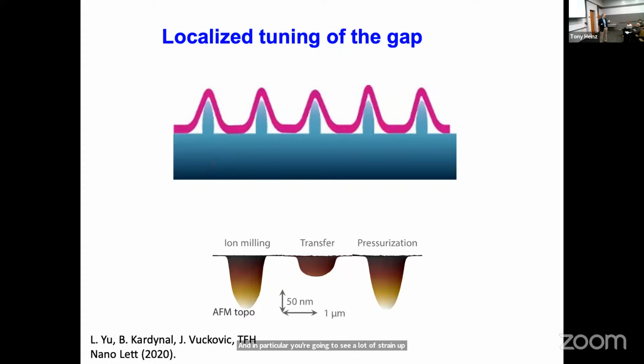This, we discovered, tends to be a pretty perturbative thing, and you do get a lot of changes, but some of them are related to tearing the material typically. We developed this sort of upside down version of this thing where we dug a little bit of a hole in the substrate, and then you could easily put the material on top of it without tearing it. If you subsequently pressurize it, you can actually make it go down into this hole. I should stress, this is also a very exaggerated vertical scale. And you create this corresponding potential well. So there are lots of interesting ideas about how you can locally pattern things and transfer the strain pattern.